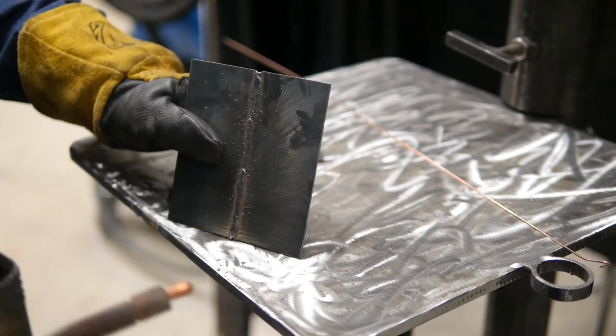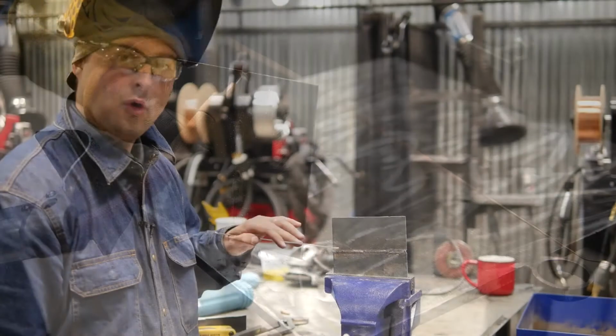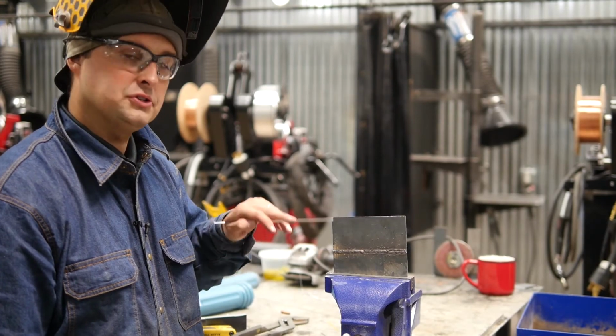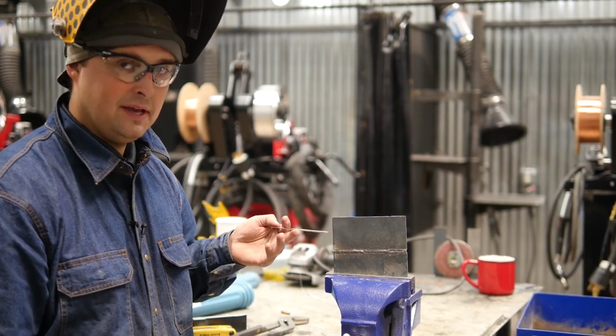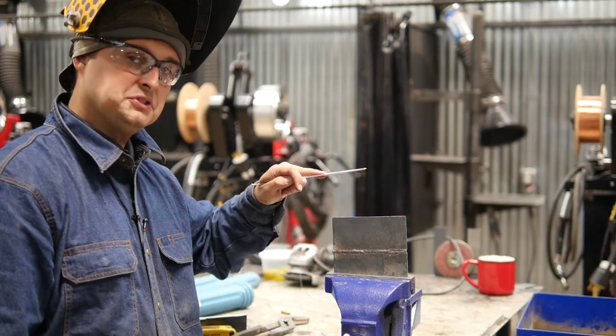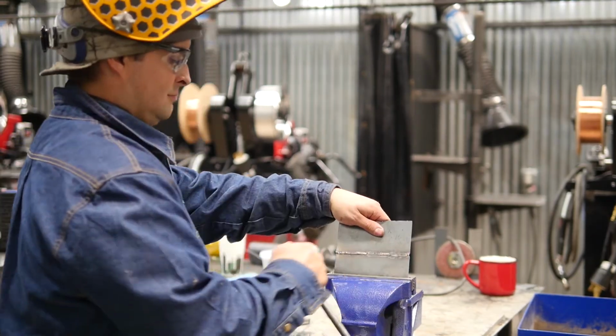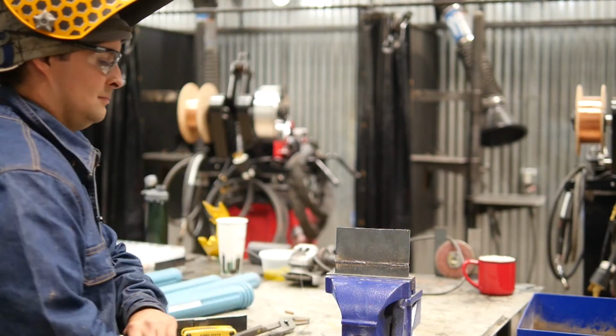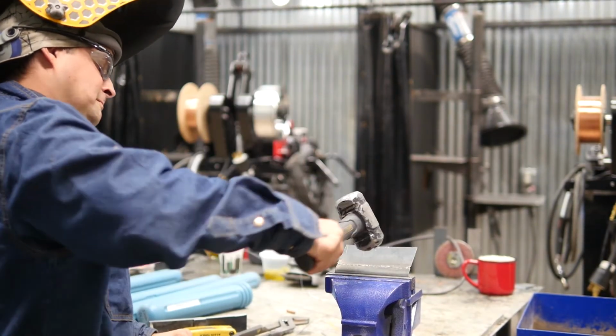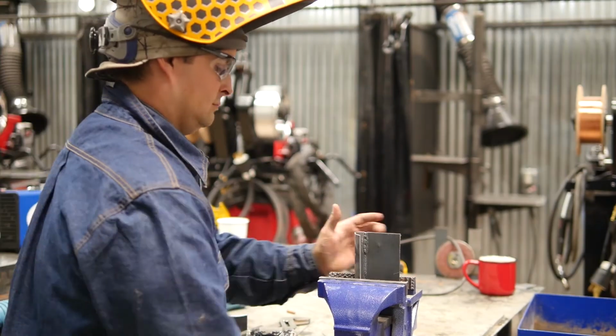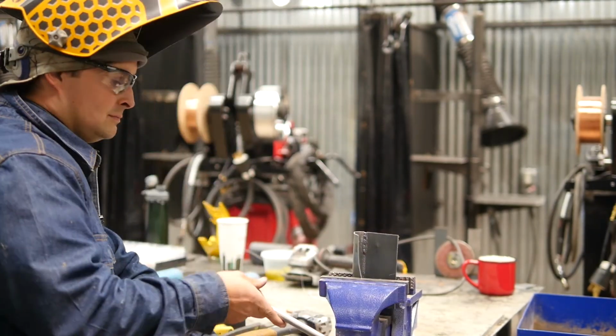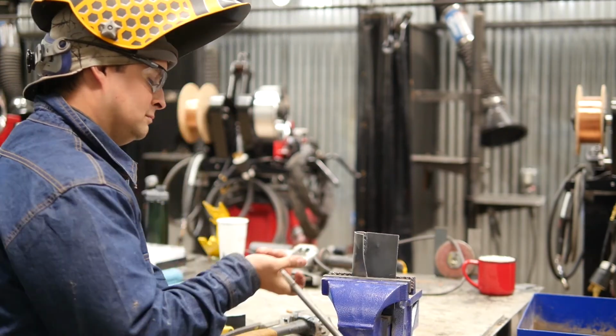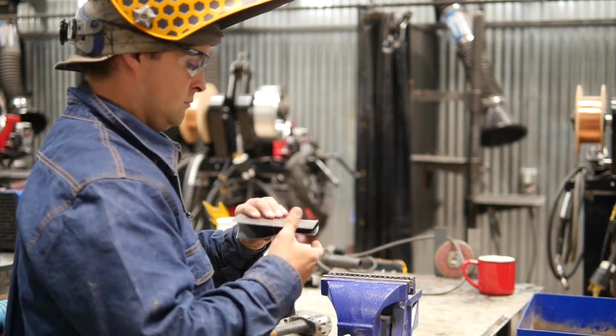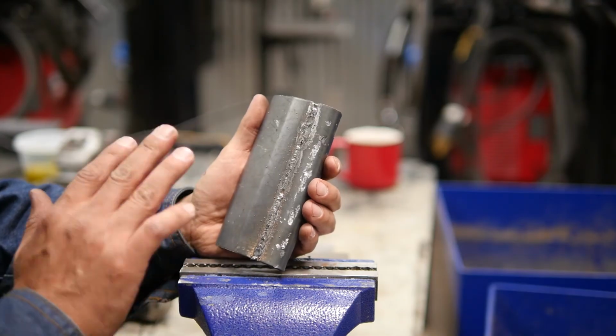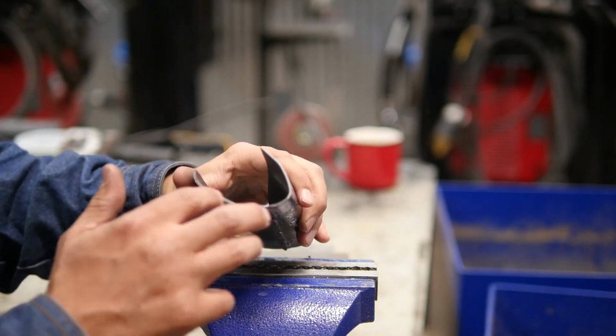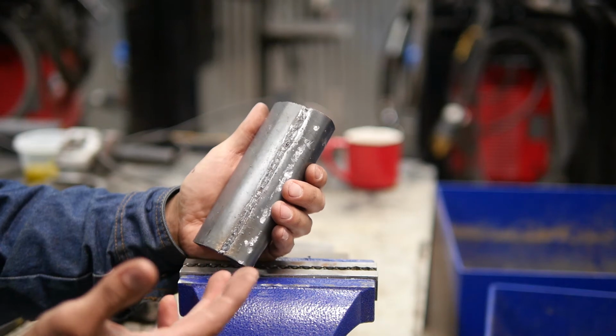We're going to fold it in half in the vise and see if our welds will perform. With steel, the weld is usually stronger than the base material. Unless our weld is defective, we should be able to bend this all the way over. As you can see, the welds survived. They performed like they should. The base material deformed around, but the welds were unaffected.